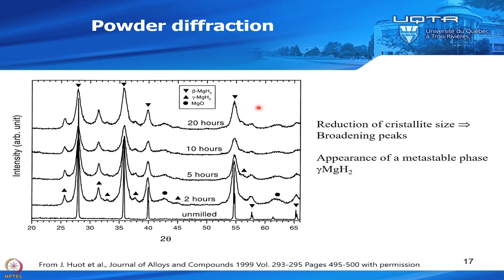So this is the powder diffraction. The unmilled one is here. And after 2 hours, you see that the Bragg peaks are getting broad. That means that it's a nanocrystalline structure. And you see that these peaks are appearing, that we did not have in the unmilled one. In the milled one, you have these peaks. Well, these peaks actually are this phase.